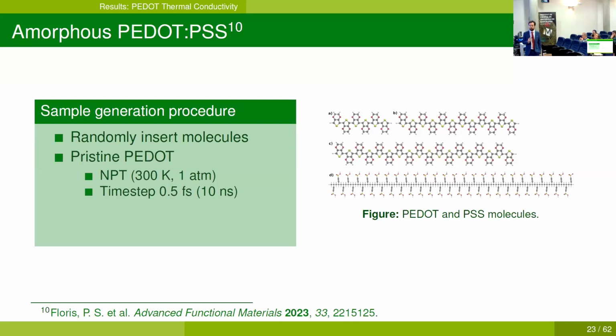And we need to differentiate between two cases. One case only contains PEDOT molecules and no PSS. And in this case, we have run in the isothermal isobaric ensemble at 300 Kelvin and 1 atmosphere with a time step of 0.5 femtoseconds for a total simulation time of 10 nanoseconds. In the case of PEDOT with PSS, on top of this protocol, we have also added annealing cycles at 1100 Kelvin.